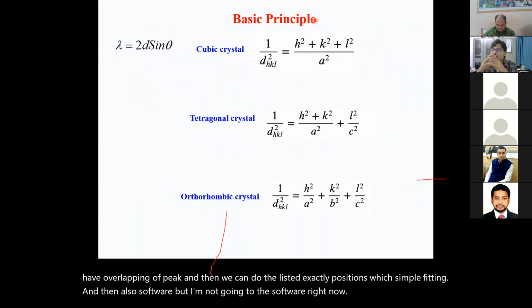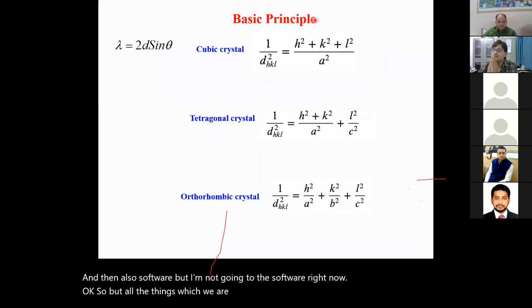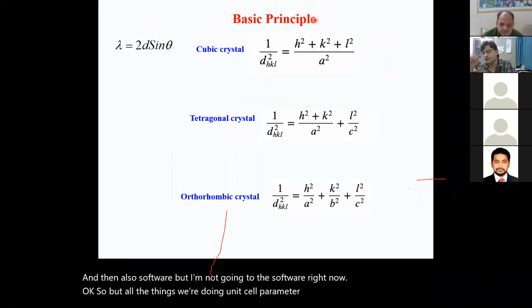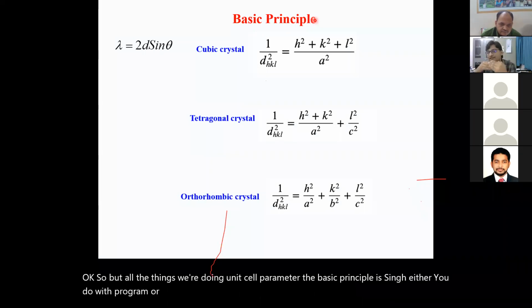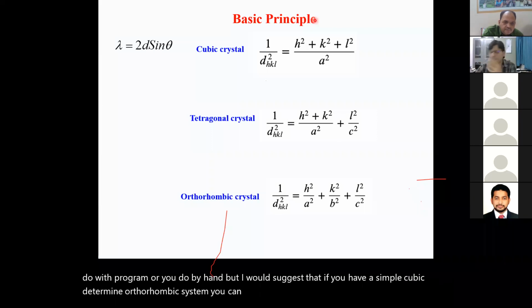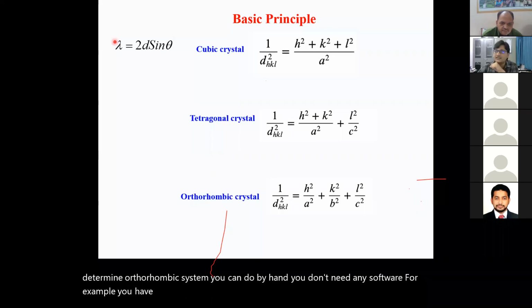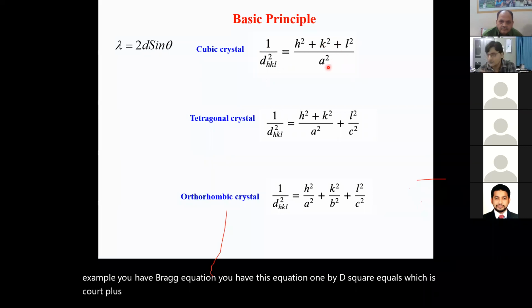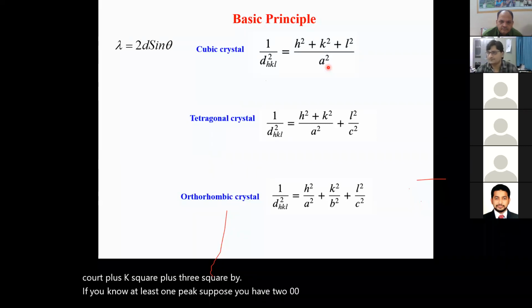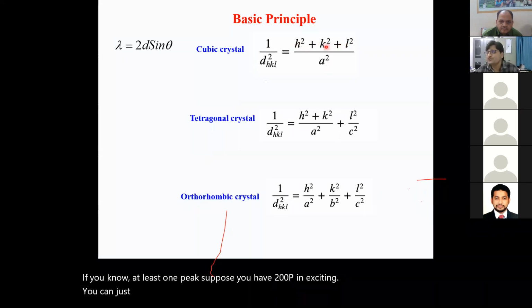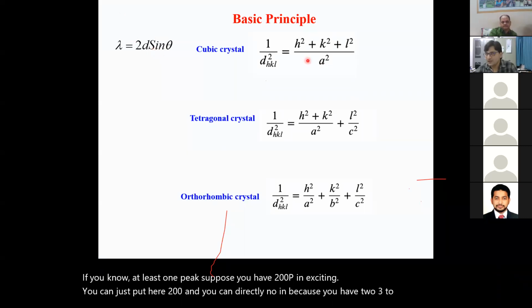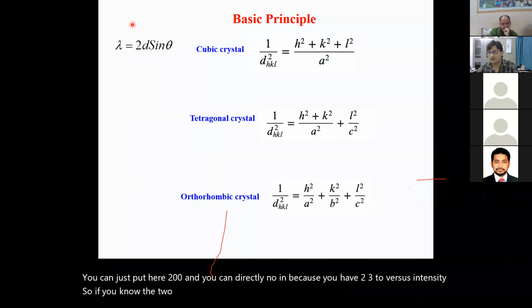But for all the things we do to know the unit cell parameter, the basic principle is the same. Either you do it with a program or you do it by hand. I would suggest that if you have a simple cubic, tetragonal, or orthorhombic system, you can do it by hand. You don't need any software. For example, you have the Bragg equation, 2d sin theta equals lambda. You have this equation, 1/d² = (h² + k² + l²)/a². Now you have one XRD pattern. If you know at least one peak, suppose you have the 200 peak in XRD, you can just put 200 here and directly know a. Because you have 2 theta versus intensity, if you know the 2 theta, you know the d from this equation.